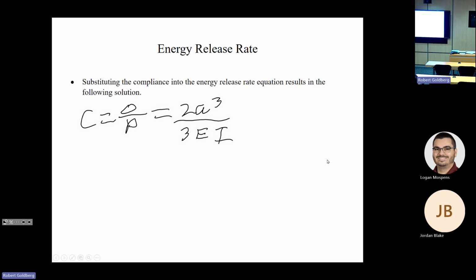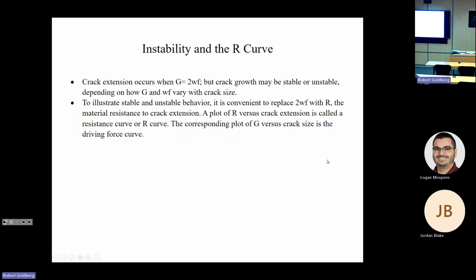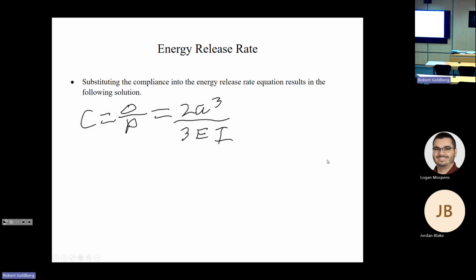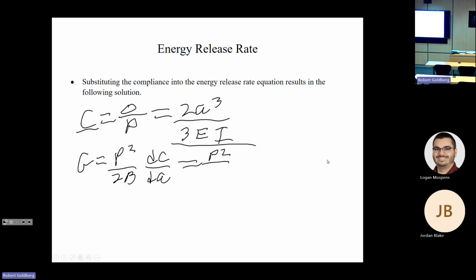So now we know that our energy release rate is equal to P squared divided by 2b times the derivative of compliance with respect to the crack length a. And so we now have our compliance very nicely defined in terms of the crack length. So we can just take P squared over 2b times the derivative of this with respect to a.